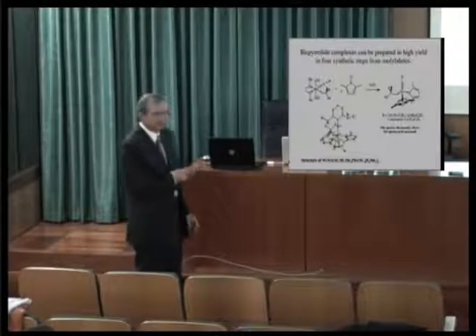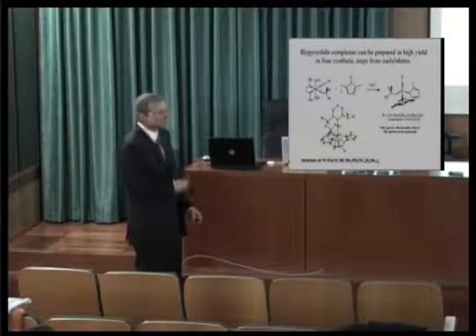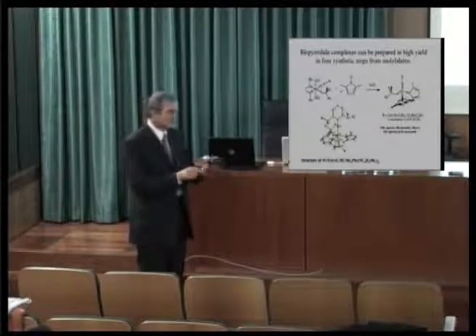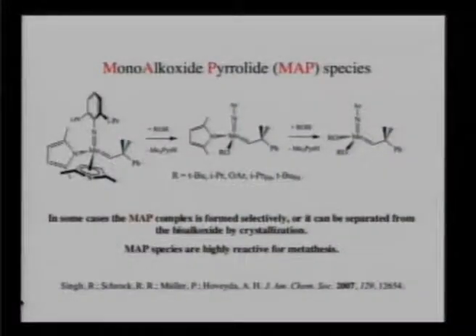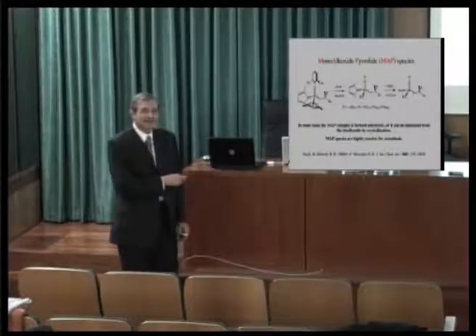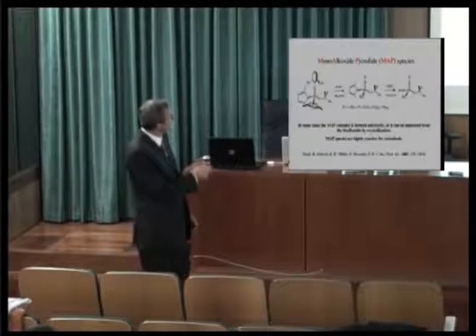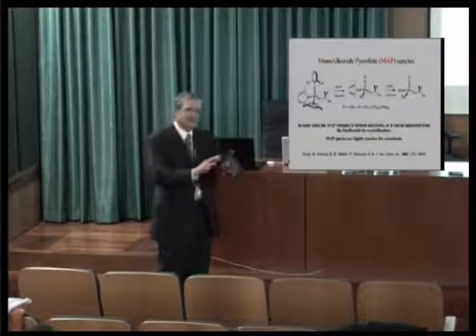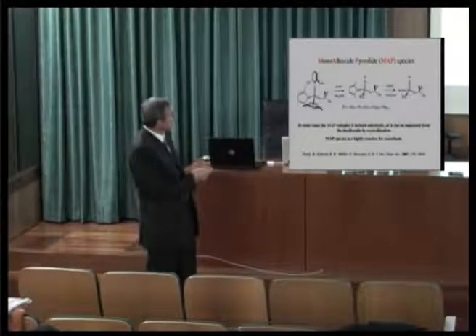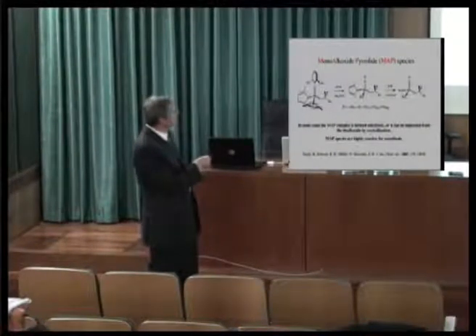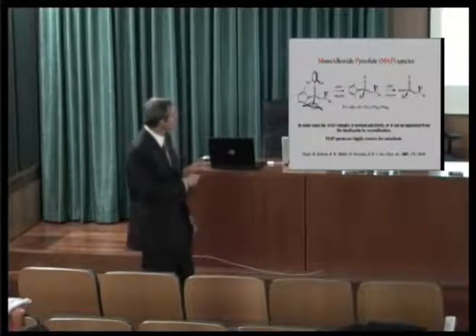We have many crystal structures of these species and know a lot about them as precursors, but we're not interested in them per se. We're interested in converting them to bis alkoxides, or were in the beginning. So this is the reaction we wanted to do. Add alcohol twice to generate two equivalents of pyrrole, here dimethylpyrrole, and the desired bis alkoxide. And we did that. We showed that the pyrrole that is generated is not binding to the metal, not interfering with the catalytic reaction. So you can make many catalysts from these precursors, putting on different alkoxides and testing them.